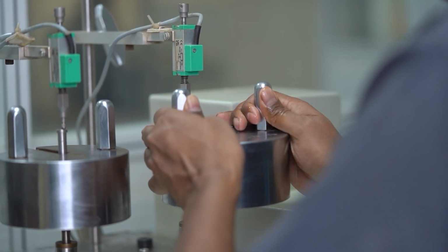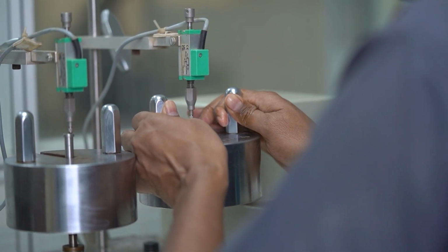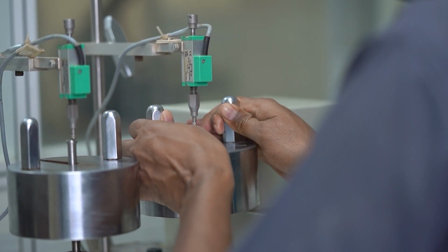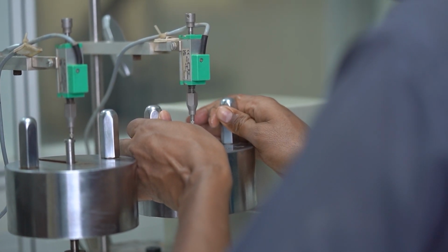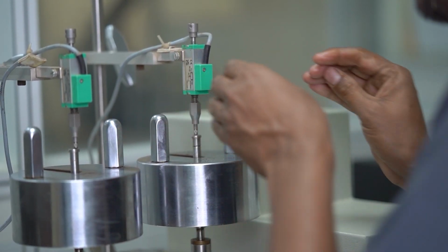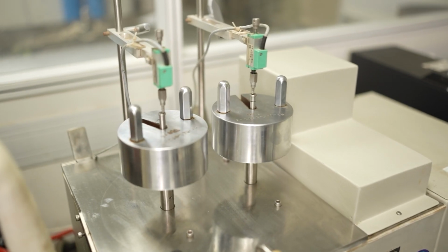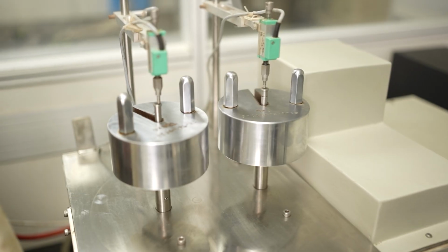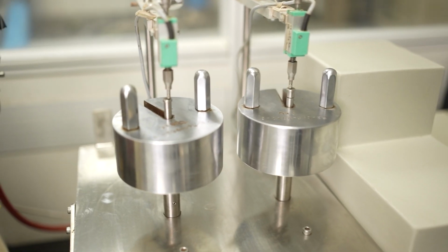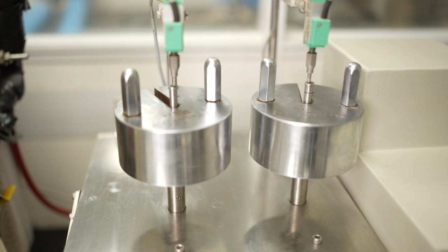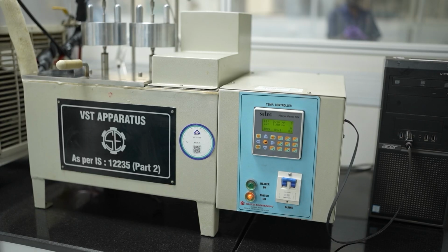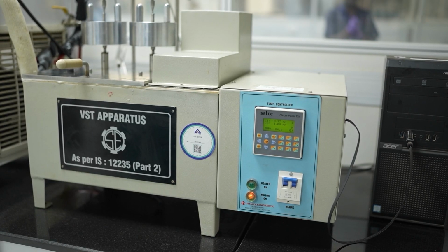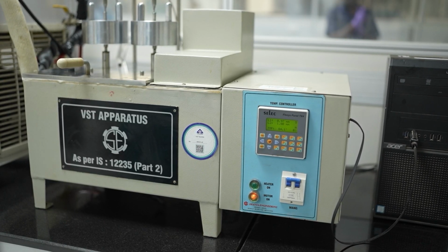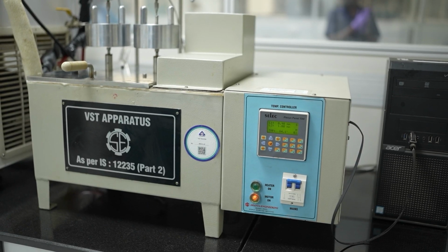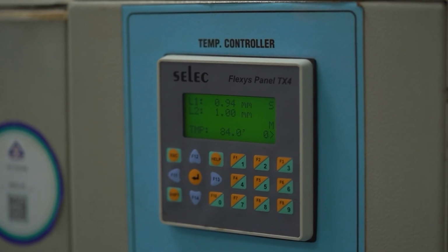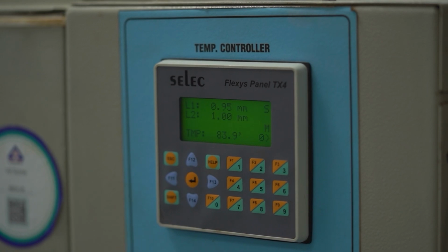After conditioning, a 50 Newton load is applied on each specimen and the temperature of the bath is raised uniformly. The bath temperature is recorded when 1 mm penetration is achieved for each specimen. The average of both readings is the Vicat softening temperature. The Vicat softening temperature of the pipe should be more than 79 degrees Celsius.